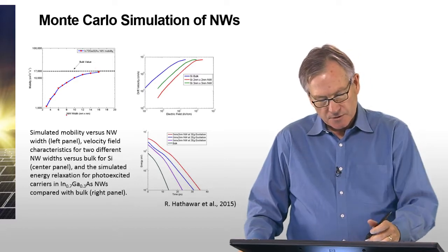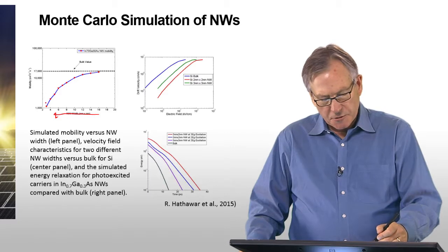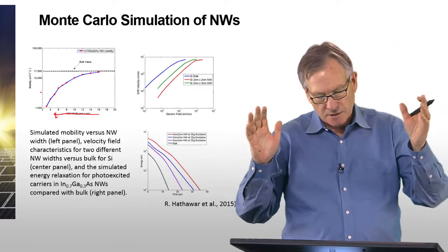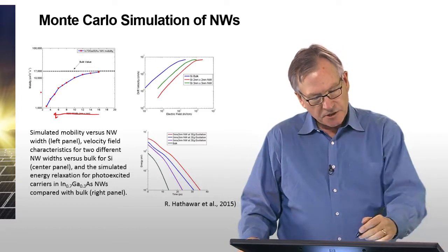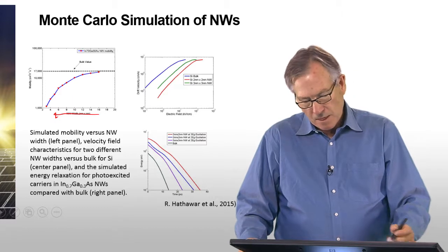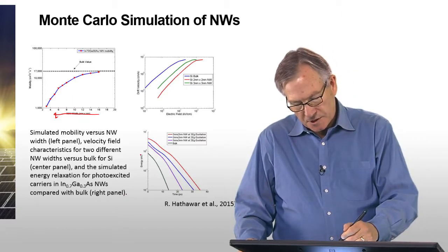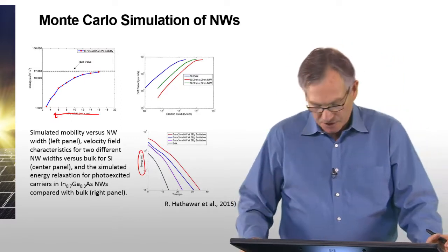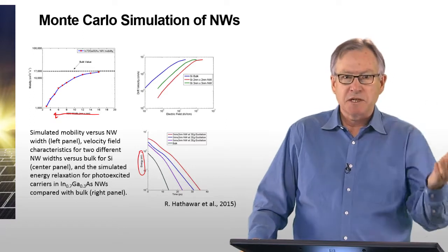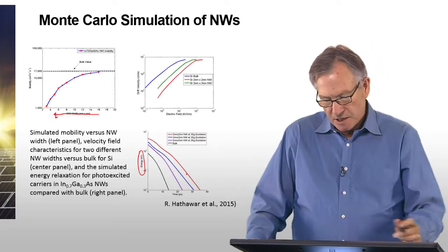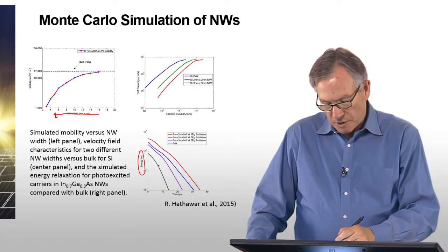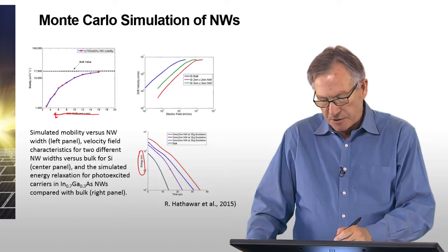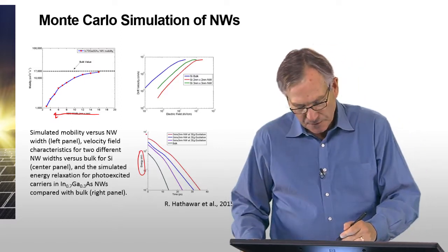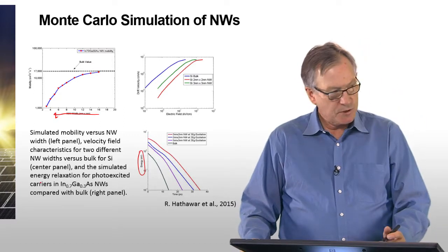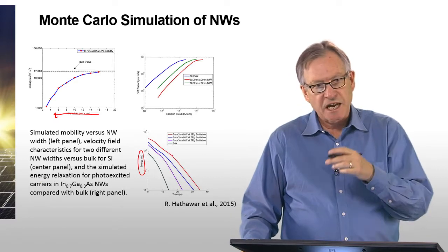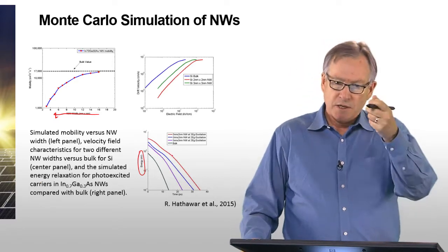As you increase the confinement, so as you make the nanowires narrower and narrower, the mobility degrades, because as you squeeze the electronic states more and more, the effective mass increases. So you get a degradation of performance in terms of the transport. But what's more important is if we look at this curve down here, this is a plot of the energy relaxation as a function of time. It's simulated by creating a pulse of electrons at high energy and watching how they relax with time. This is the bulk rate, which is quite fast, but you can see that for a 3 by 3 nanometer nanowire and 2 by 2 nanometer nanowires and different excitation energies, the rate of relaxation becomes much slower. In fact, you can get a 2 to 3 times slowing of the cooling rate just by going from a bulk material to a nanowire.